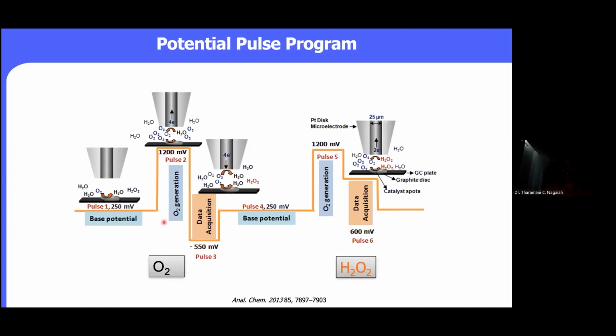So that means during the oxygen reduction reaction, we also face hydrogen peroxide production. This production one can also simultaneously monitor. And this is actually the customized one. Depending on the application, one can fine tune this. You can see here the oxygen reduction reaction and also the oxygen production here. And again, applying the base potential, whatever hydrogen peroxide you were producing is again reduced back to the water. And indirectly, you can calculate the amount of hydrogen peroxide also.